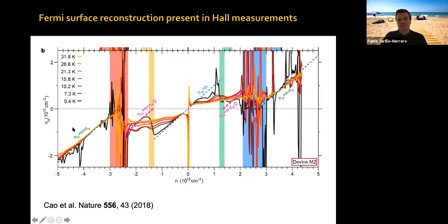This is in the supplementary information of the paper, of a Fermi surface reconstruction present in Hall measurements. When you do Rxy measurements at small magnetic field, this is complicated because it has the complete temperature dependence, but just look at this black trace. There is a big reset of the Hall density, indicating a reconstruction from a large Fermi surface to a small Fermi surface. Of course, now with these inverse compressibility measurements, we know that it has to do with the system occupying a big Dirac cone, resetting now to near the charge neutrality point, in this Dirac revival.